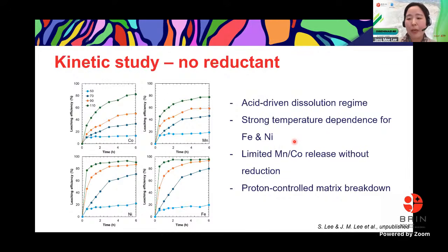So this is basically the acid-driven dissolution, because we haven't used the reductant for this study. And then you can see here all of the metals like cobalt and manganese and nickel and iron are temperature dependent. But as compared to the nickel and iron, the cobalt and manganese are somewhat limited in terms of the leaching efficiencies.